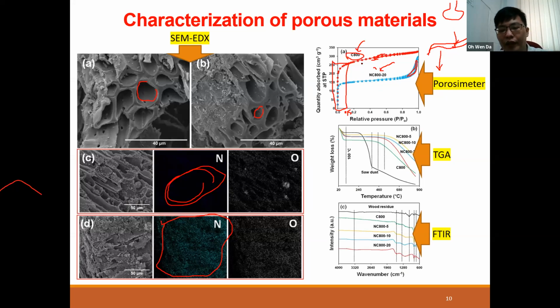Very interesting, especially for the adsorption process. All these will affect the adsorption. When you have ink bottle pores, something like this, then you probably will have good adsorption. Then all the adsorbate will be here. But when you want to carry out the desorption process, that will be a problem because all these adsorbed species have to go out from the same small hole here. So desorption will be a lot slower. All this will tell you a lot about the adsorption phenomena.